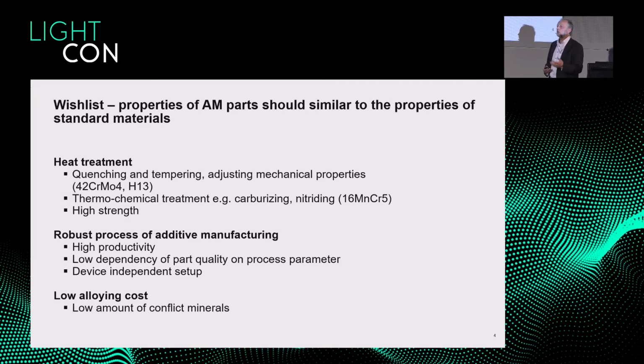And this heat treatment and quench and tempering process is a very nice property of steel, because you can adjust the mechanical properties by the heat treatment. You can adjust toughness, strength, hardness to your needs. This is a very nice property, but it causes some difficulties, as shown later. We can also do a so-called chemical treatment. We can carburize, we can increase the hardness of the outer shell of the material. You can build gears or bearings with this procedure. One of the steels is a 16MnCr5. I think it's always used if you have a car. It's produced in mass. We are here at the LightCon, so one point on the wish list is high strength